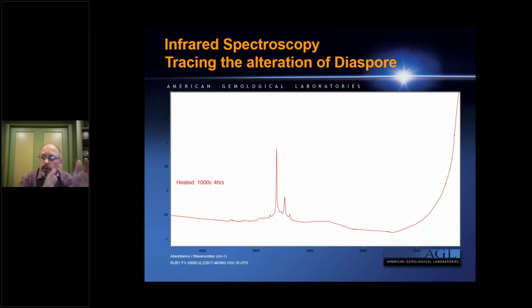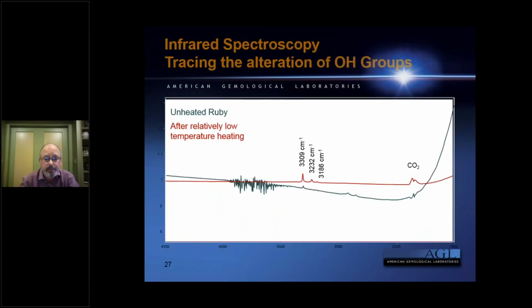And so you convert the aluminum hydroxide into aluminum oxide, and the hydrogen is then diffusing into the lattice where it's creating structurally bonded OH groups. So you can see this transition take place in the infrared spectrum. Even though you might have inclusions that may not give you clear guidance on whether or not the Mong Hsu ruby has been heated, infrared can help you very much.